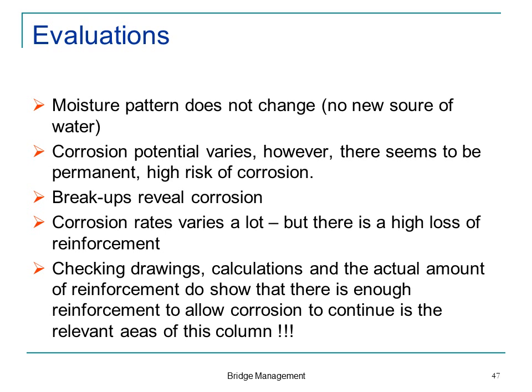That means those areas where there is the most moisture right now will probably also be the spots that have the most moisture in 2, 3, 5 years' time. The spots with the high risk of potential don't really change. But corrosion rate seems to vary quite a lot.